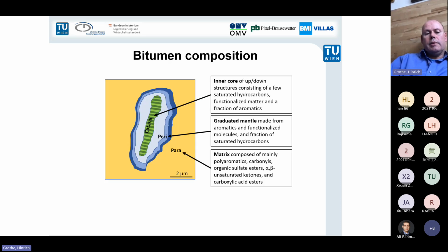So just to summarize that a little bit, we have the katana phase. This is up and down. This is the inner core, and consists of a few saturated hydrocarbons, functionalized matter, and a fraction of aromatics. Then we have the paraphase, which shows also a gradient and is made from aromatic and functionalized molecules and a small fraction of saturates. And then you have the matrix around the paraphase, which is made up mainly of polyaromatics and a smaller fraction of carbonyls, esters, and ketones, and so on. And this can all be analyzed with infrared spectroscopy and the different surface techniques.